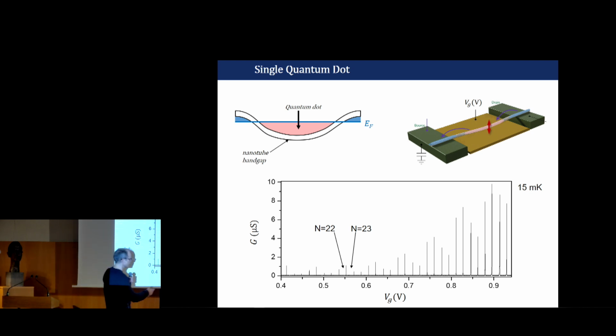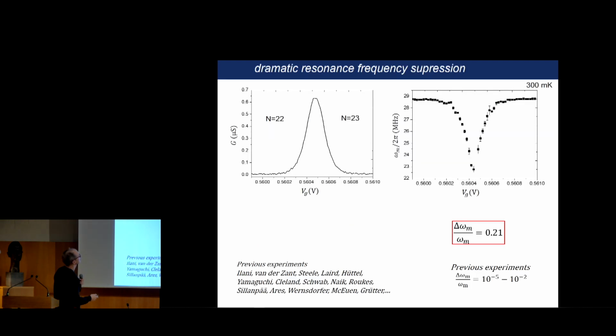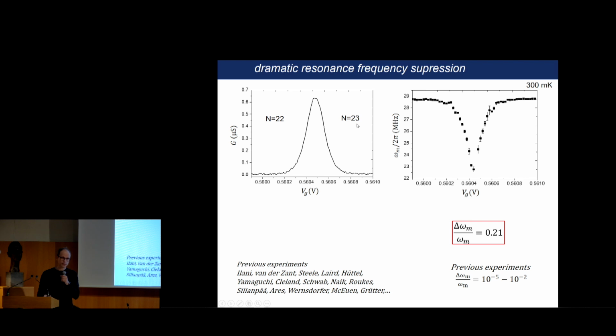And now what I will do is to zoom on this peak. And so this is what you get. So here is the conductance as a function of gate voltage. The conductance is 0. Here at the peak, what we have is that the system is fluctuating between the 22 electron state and the 23 electron state. So it's a two-level system, but it's a bit special because the two levels are degenerate. And so at this peak,